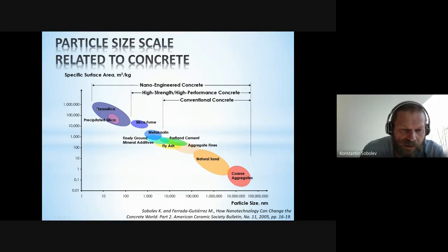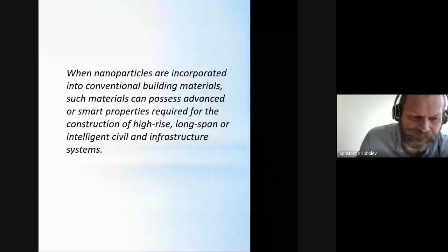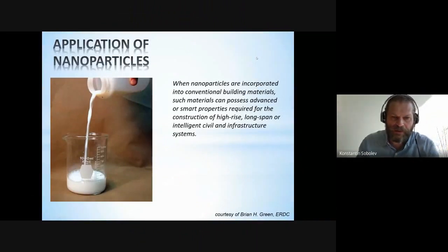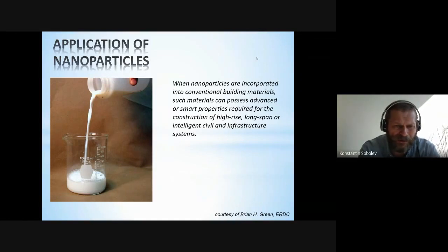Now, when we have smaller components with higher surface area and higher reactivity, we can produce nano-engineered concrete. Nano-engineered concrete is not only high-strength concrete, not only concrete tuned for extreme durability, but also concrete with special properties which we can achieve by incorporating different nano products. Not necessarily nanosilica, but any other nanomaterial can be used. When we speak about nanoparticle application, proper dispersion is extremely important, because if nanostructures are not dispersed, if they are present in the form of agglomerates, they are not nanomaterials themselves.